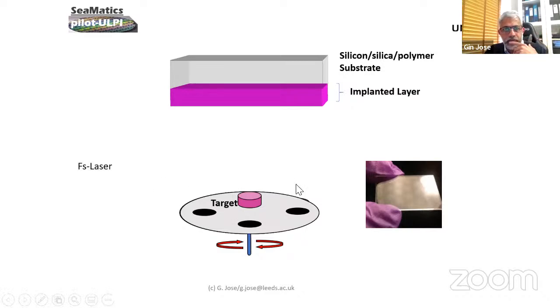So in this process, it's similar to the previous process. We optimize the conditions within the chamber, and we also heat the substrate, in this case silica-based glass, so that you get this material to be mixed with the silica and essentially form a new silicate glass at the surface. The advantage of the process is that you can control where you want to modify on a substrate. You can use a mask to control where you want to produce the changes. Here you can see the openings of the mask where the material is being diffused into the glass.